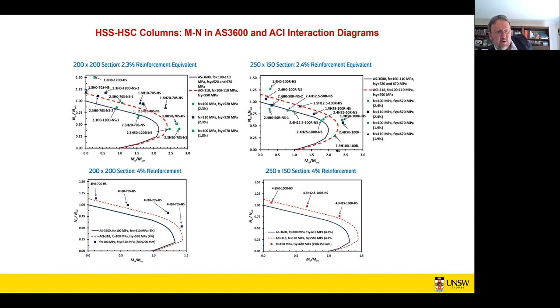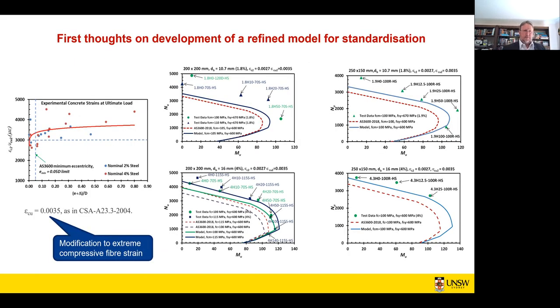It's actually, the ACI model is quite a poor predictor. It actually overestimates the strength, even though it underestimates or gets the strength about right for the high strength steel. So the high strength steels here are the blue triangles on this specimen, and the green squares on that specimen. So we can see here, we're not capturing with great accuracy the test results. We're leaving a certain amount in the cupboard, if you like. We're not getting as much out as we can or should be doing. So let's have a look at that in a little bit more detail.